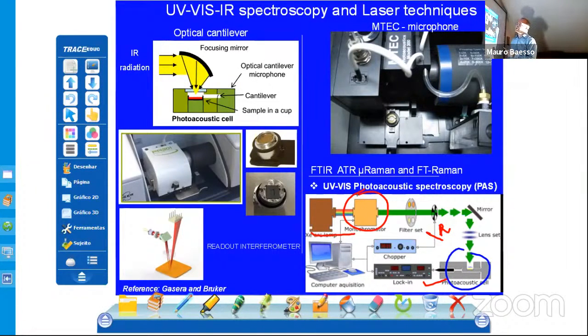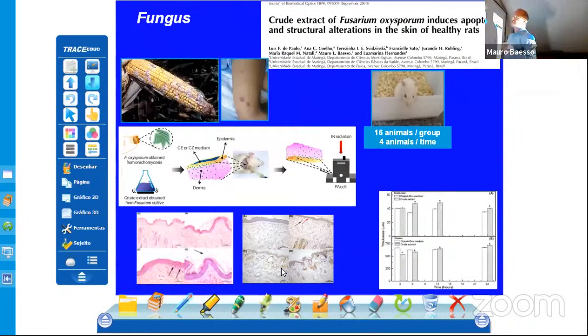But of course, there is commercial equipment today that you can use with FTIR detection, like this cantilever microphone on the Gasera cell, and then you can do the whole spectrum in the infrared by FTIR, and you can also measure the absorption coefficients of the samples in the mid-infrared and near-infrared. The idea, of course, when you go to the mid-infrared, as I said before, is to look at the functional groups of the biological tissue and how it changes with some disease or any changes you try to induce in the tissue. Okay, so these are the two photothermal spectroscopies, photoacoustic, that we can have. You have no commercial equipment in the UV-visible. This is homemade, but you have commercial ones for the infrared.